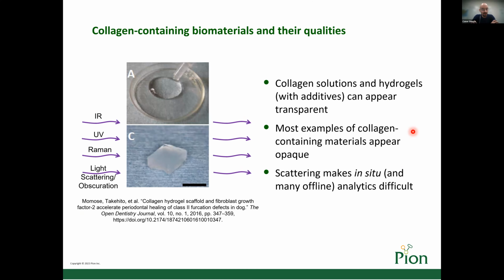So just a quick last mention, one more barrier, and that is actually what happens when you introduce collagen and structural proteins into an aqueous environment that's supposed to mimic the in vivo. Up here, we have a very typical example of a collagen hydrogel that was formed at ambient temperature with solubilized collagen. Most collagens, when they are solubilized, can exist in a clear solution. And in the bulk of publications in science put out thus far, the resulting collagen-based hydrogel has been opaque in nature, simply because collagen loves to assemble on itself. It wants to try to form those fibers. It wants to try and form solid materials at neutral pHs. And so this is what the bulk of materials have looked like.